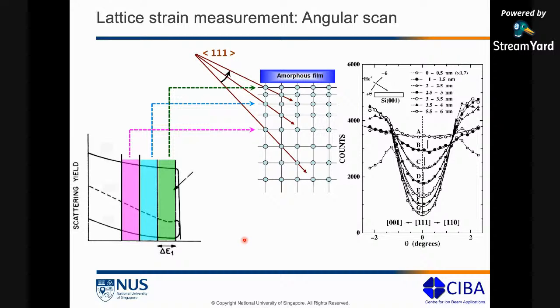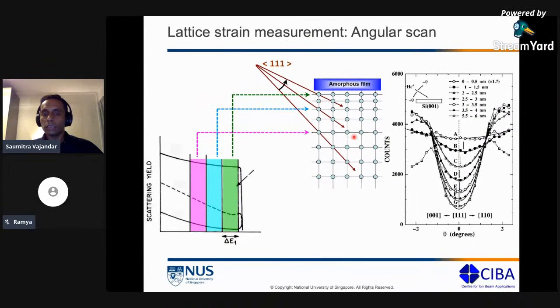All right. So once we have these five spectra, we put them together on one graph, superimpose them, and we split the x-axis, or the energy scale, into these different regions. So what do these regions mean? This is the high energy region, which corresponds to an area closer to the interface. This region comes at a slightly lower energy, which means it is coming from somewhere much below the interface. And this region comes at an even lower energy, which means it is coming almost from the bulk, where the strain is not affecting the crystal structure. The crystal structure is quite good, right?